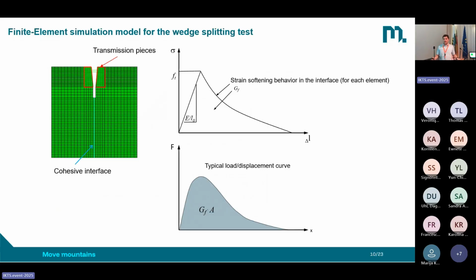So now you may ask, is this assumption that we have this combination of tension and bending justified? And the question is not that easy to answer, but what we could do is a finite element simulation and simulate the stress distribution in the sample. And this is what you see here. We have a model of the wedge splitting test. Here again, a cubic sample. Then we have the load transmission pieces. We have the wedge moving downwards. And then we assume here in the center a cohesive interface. This means here the crack can propagate.